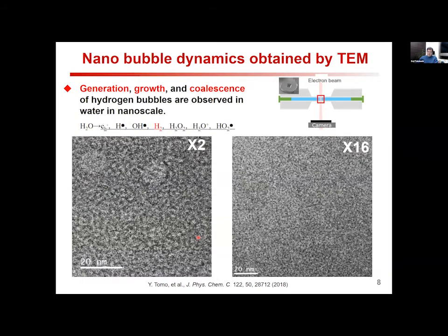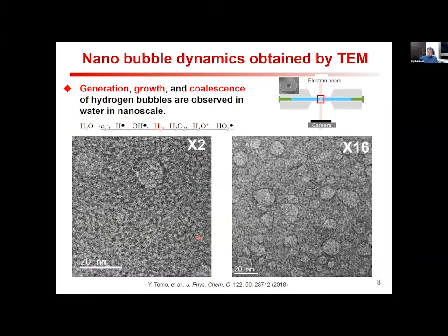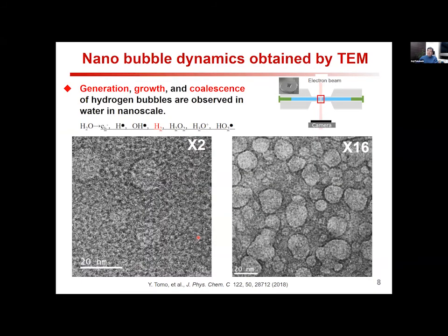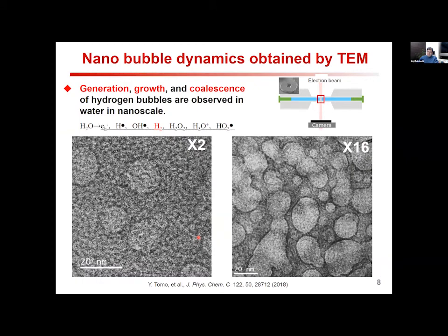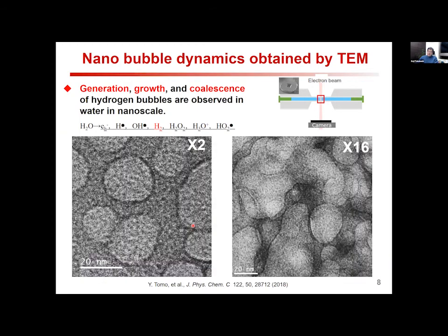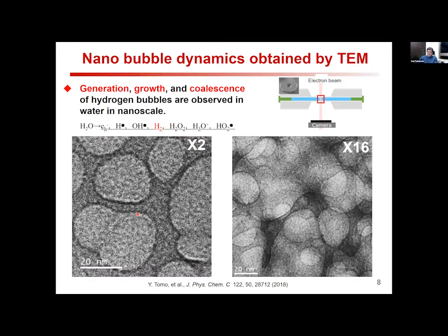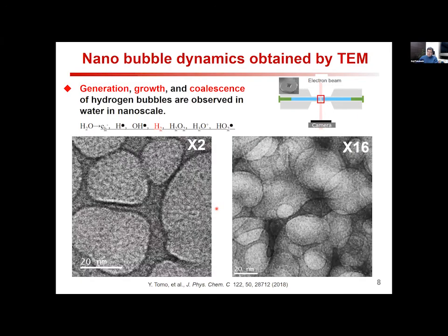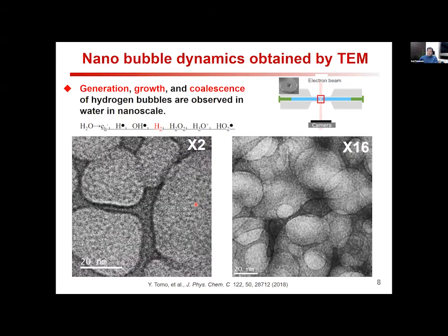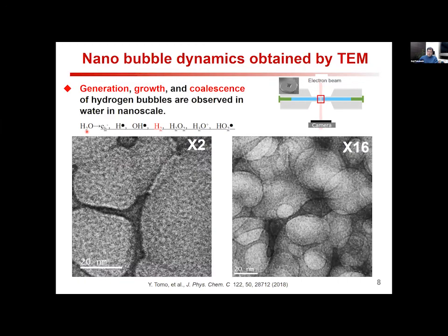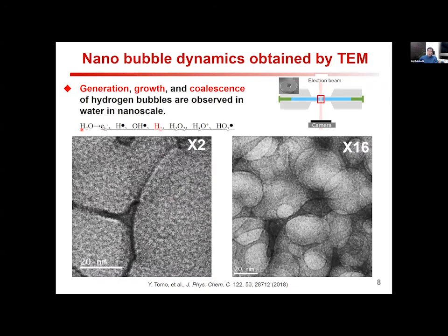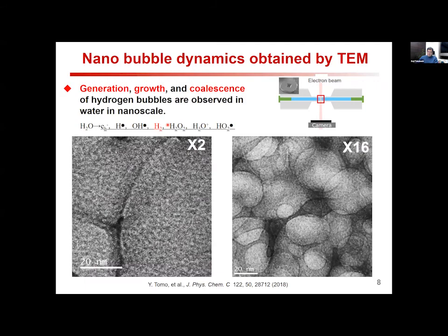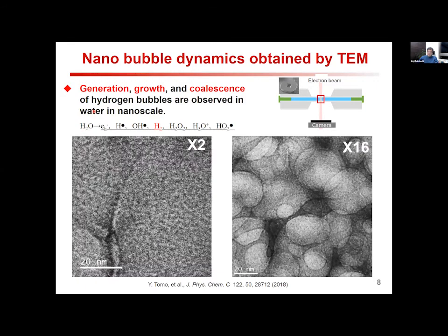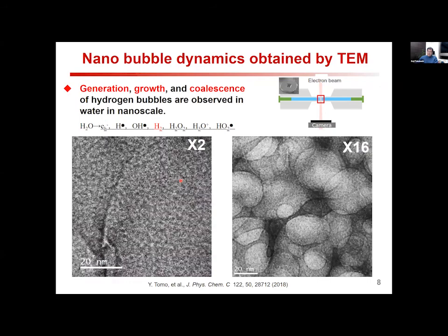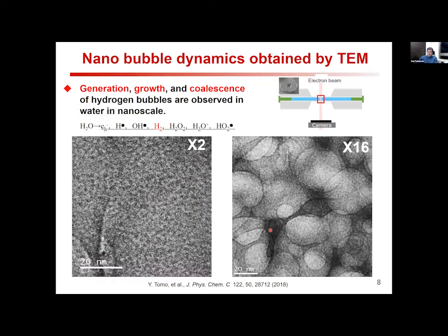In this slide, I'm showing 2 movies of nanobubbles using TEM. Bubbles are generated and we can see their growth and coalescence. But these bubbles are hydrogen bubbles produced by radiolysis of water molecules induced by electron beam. But these movies allow us to understand what is different between nanoscale and macroscale bubbles.